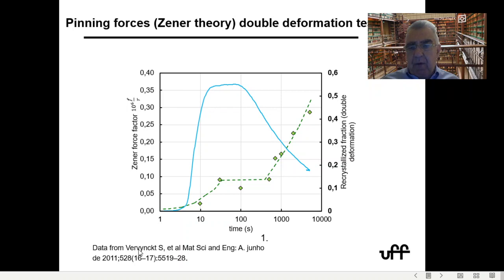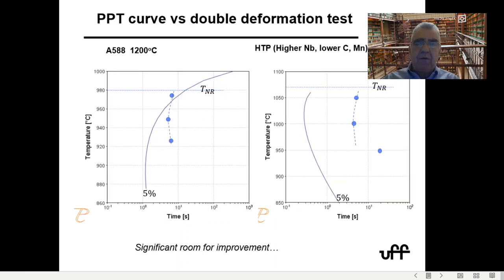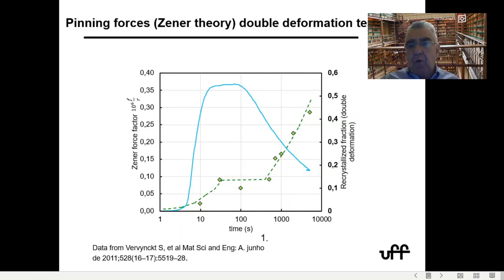This is when you get the data from the model, and instead of just looking at the volume fraction precipitated, because this is, let's say, a real simplistic way, because you're not taking into consideration the size of the particles. Now, if we go back to Zener's theory and we say, well, Zener factor depends on the volume fraction divided by the particle radius. So now I can plot for 1000 degrees, which was one of the experiments they did. I can plot the Zener force, and I say, well, there's a maximum Zener force here to prevent grain growth, and then it starts decreasing, and it's probably not going to be able to prevent recrystallization at some point. And these are the results of Reich. I mean, it's a classical double deformation. It stops here, the recrystallization, then you have some time. And why do you have some time? It seemed like as the particles are coarsening, the Zener factor is decreasing, and then you're having the recrystallization again.